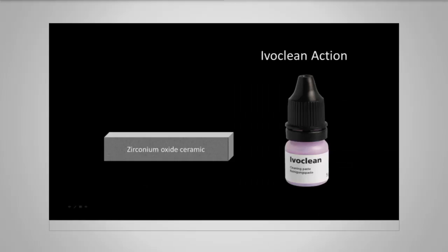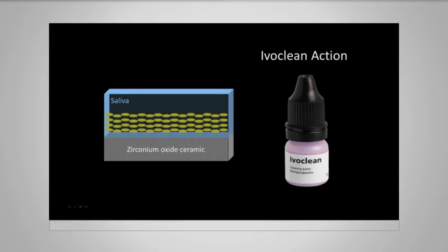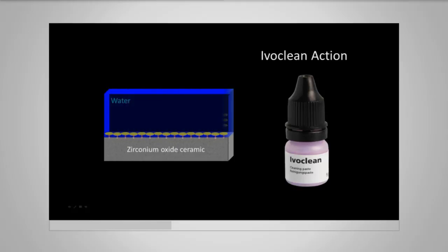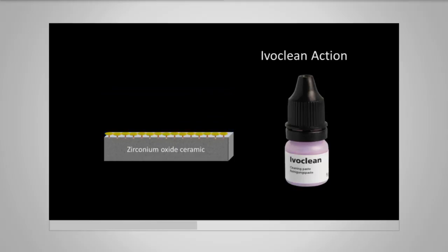All right, and I'm going to walk you through this. So here's a little video. So you take your zirconia, and when you try it in, you get saliva on the zirconia. Inside saliva, you have phospholipids. Now, phospholipids have a high affinity to the zirconia because it wants those phosphate groups, right? And so when you would wash it out, all those phospholipids would still be stuck on the zirconia. And they would take up all the sites that were reserved for the resin, right? The phosphate groups of the resin.